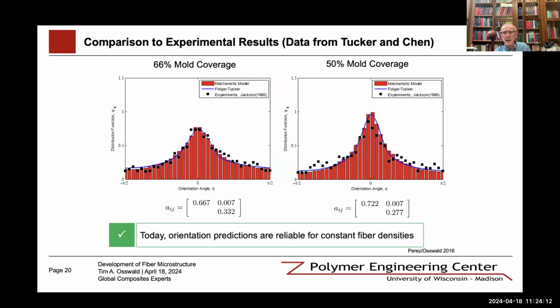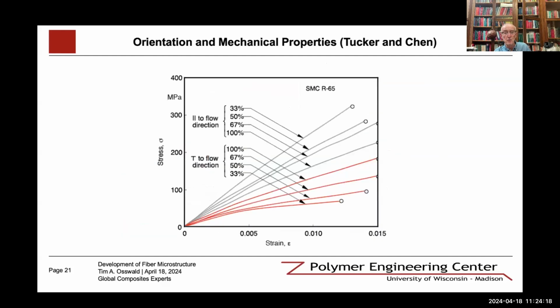Today, orientation predictions are reliable for constant fiber densities, and we know that fiber densities, of course, vary. This is the data from Tucker and Chen, where we can see the need for having orientation in the final properties. If we concentrate on the lowest curve and the highest curve, that's in the direction perpendicular to the fibers and parallel to the fiber orientation for the 33% mold coverage. So we have a charge that is 3 times as thick as the final part, so there's quite a bit of deformation, which is not atypical for compression molded parts.